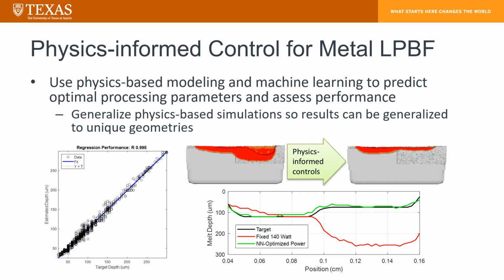On the left side is what we would expect to see if we didn't have this intelligent control process. So the red information, pull up my laser pointer. All right, this red information here is showing the melt that's created by the laser. And the profile of that is seen on the image below. You see it's got a lot of variation here, where the black line on this bottom graph was our target melt depth. So there's a lot of error between what the system's doing and what we wanted it to do.